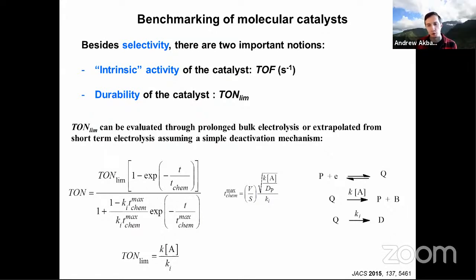But as a quantity that should be reported, is it better to report the turnover number or the lifetime? I would say that probably the turnover number is better for a given situation, for given conditions, because as you can see here, the maximal turnover number will depend on the lifetime of the catalyst in the given conditions, divided over the rate constant, which also depends on the conditions, if you have co-substrates and so on. Okay. I also saw somebody turning on the microphone. So if someone wants to ask directly a question, please go ahead.